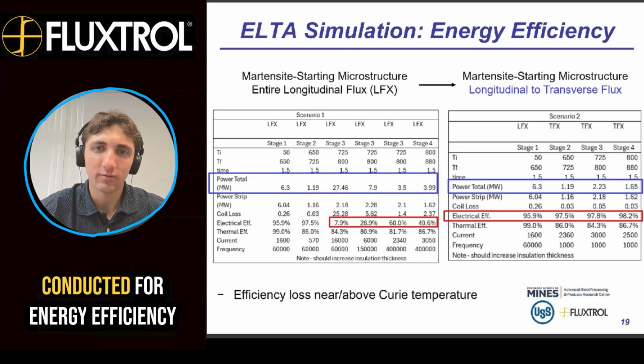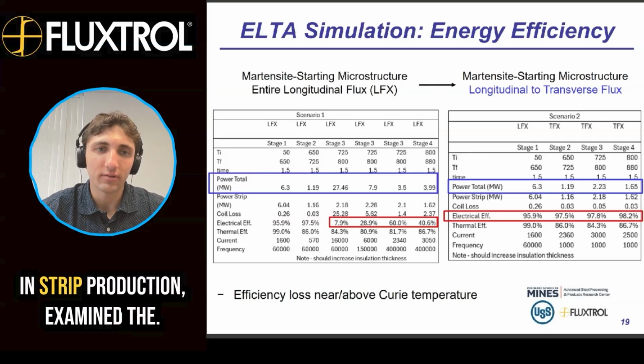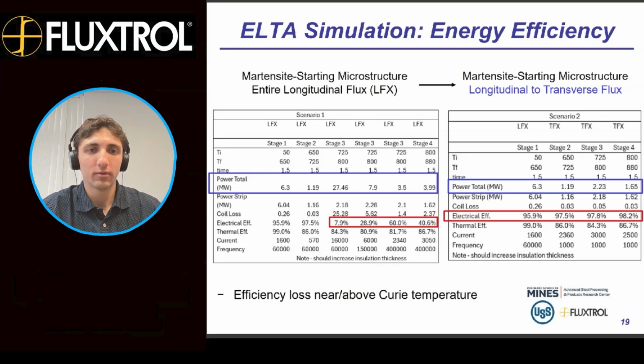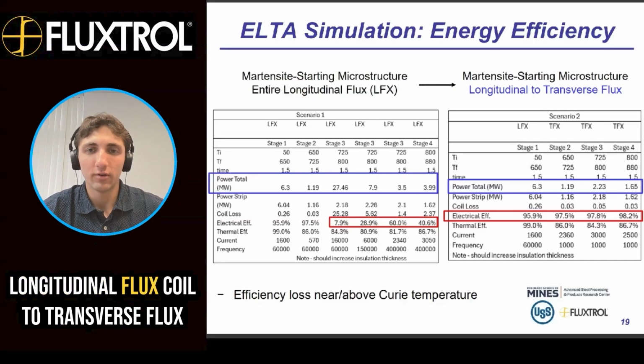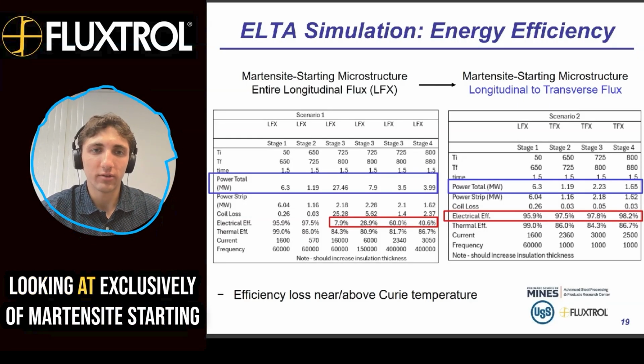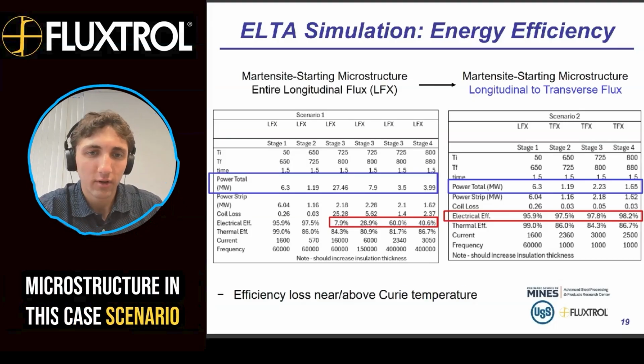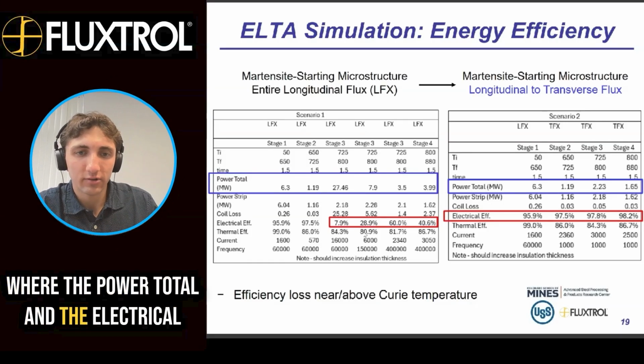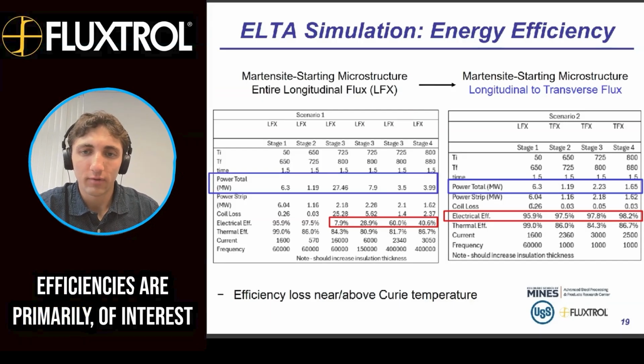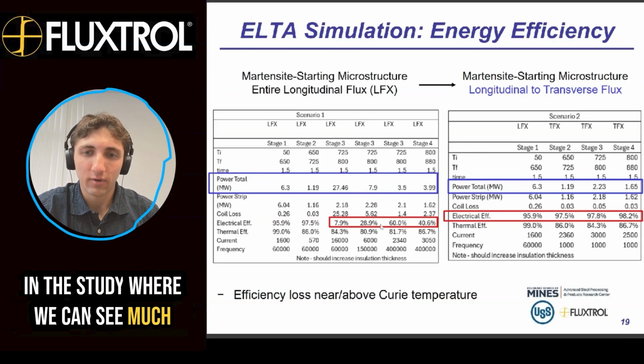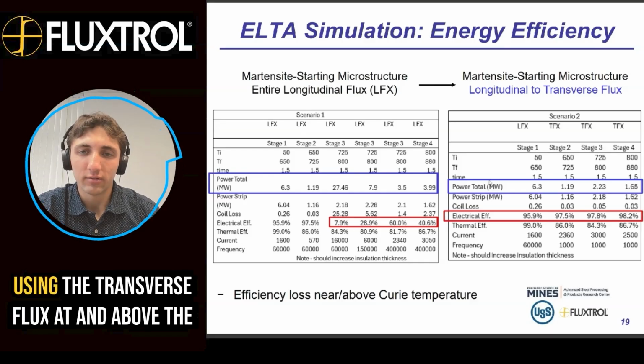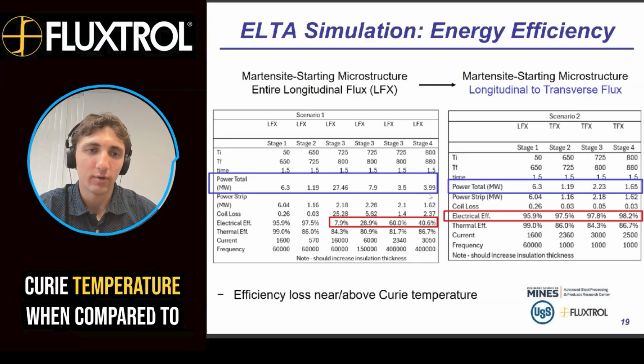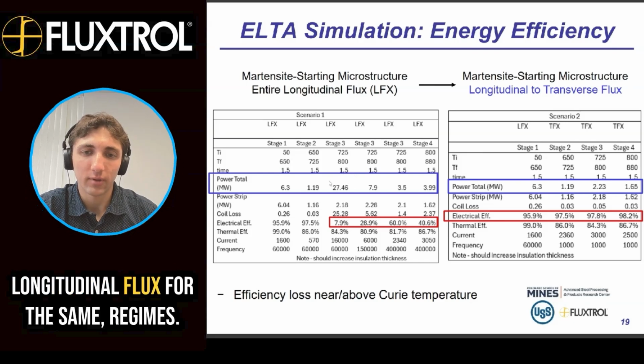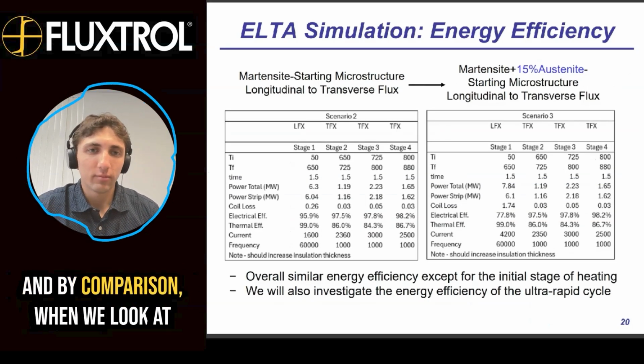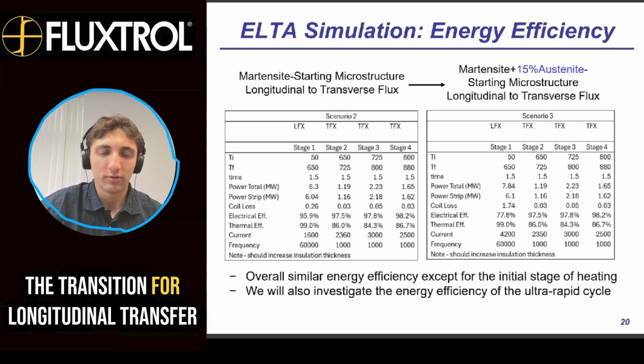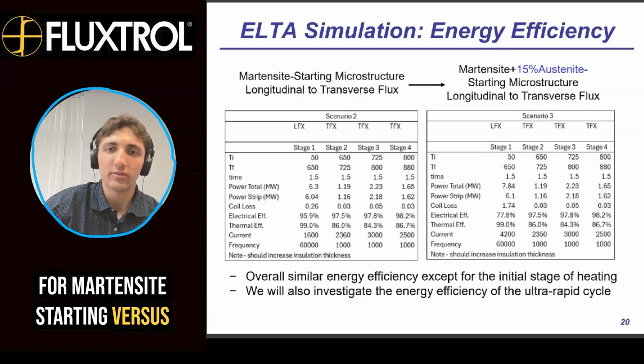When looking at the Ansys simulation conducted for energy efficiency in strip production, we examined the impact of switching from a longitudinal flux coil to transverse flux, looking at exclusively a martensite starting microstructure in this case scenario, where the total power and the electrical efficiencies are primarily of interest in this study, where we can see much better electrical efficiency shown using the transverse flux at and above the Curie temperature when compared to longitudinal flux for the same temperature regimes.